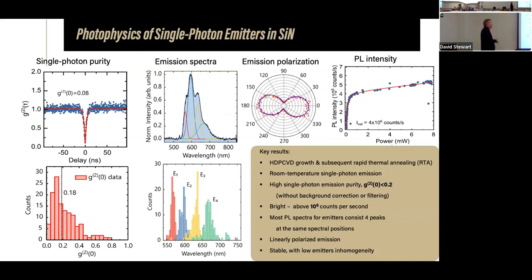So in terms of their qualities, it's all room temperature measurement. So please remember, for room temperature it's quite impressive quantum purity, 0.08, below 0.1. Basically, lots of emitters have this autocorrelation function below 0.2, and this tells you how pure your single photon emitters are, because G2 characterizes that you really have a single photon rather than 2 or 3, and ideally it should be 0, of course. The polarization is linear as expected. The number of photons is quite large, actually approaching 10 million.